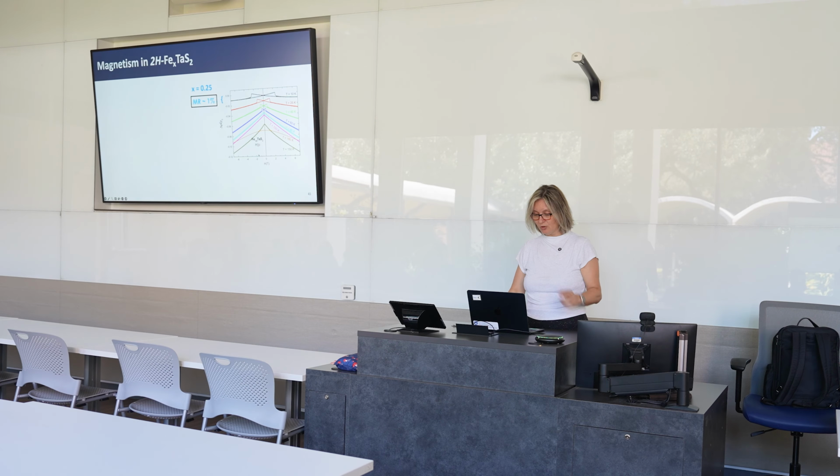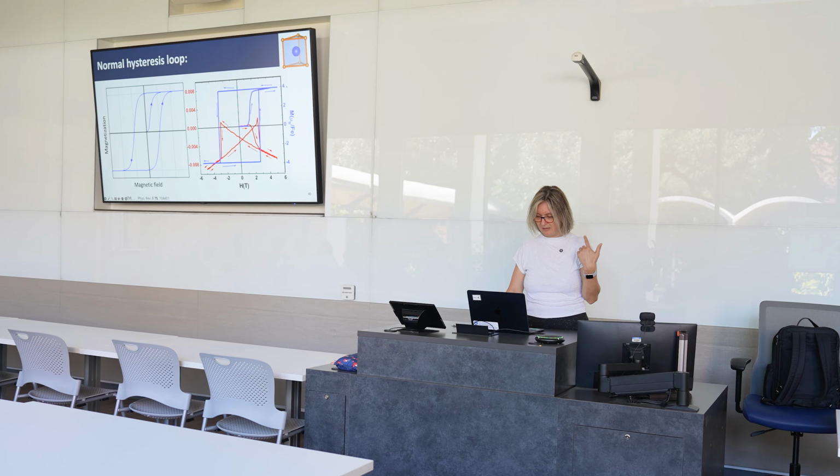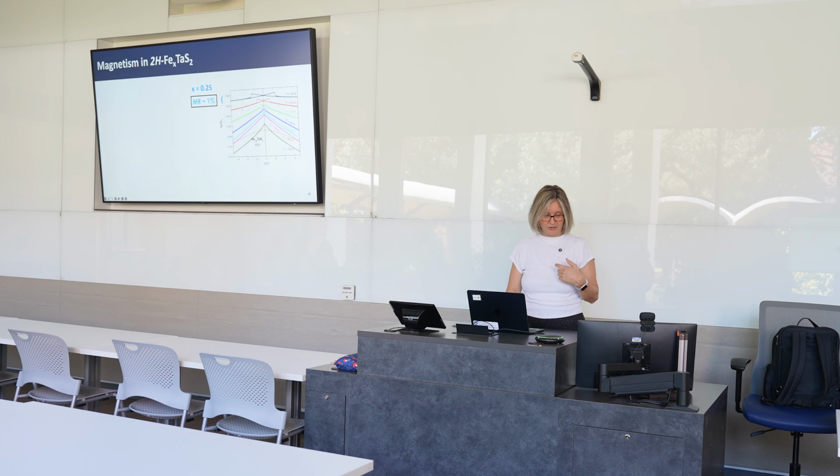And when we now look at the magnetoresistance as a function of temperature, the black curve over here was the lowest temperature. Before I showed you actually an even lower temperature. What was that? I didn't write it over here, I'm sorry. It's 2 Kelvin. But even as we go to higher and higher temperatures, the magnetoresistance has this bow tie shape and the very sharp switching, up to about 100 Kelvin.